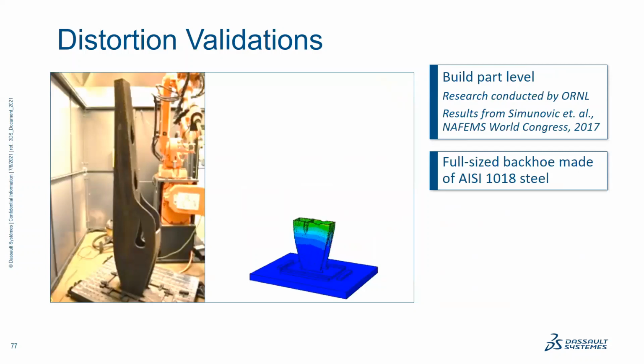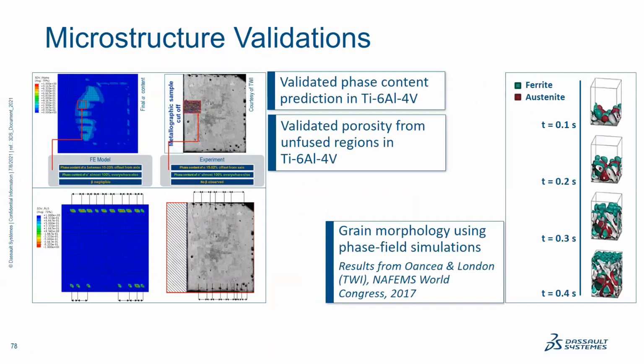And for the actual part level, this is a part of an excavator arm, which was printed by a big area additive manufacturing machine. And this is printed with steel and is part of the research work done by Oak Ridge National Lab. And further, additionally, to capture the microstructural solidification accurately, you need to go in for microstructural validation also. So as you can see here, the published work focused on grain morphology validation through phase field simulations to identify which are the regions where you can have porosity, where there is not enough good fusing of the powder, and the possibility of defects which can occur.